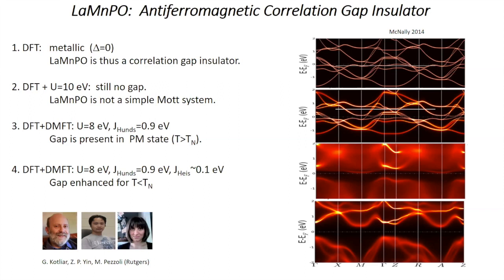So there are 4 panels that are shown at the right that develop our argument. And the top one would be the results from DFT. And you can see that at the Fermi energy, there is no gap. And so if DFT predicts that this is metallic, while the experiment says that there is a gap, we can construe that this compound is a correlation gap insulator.